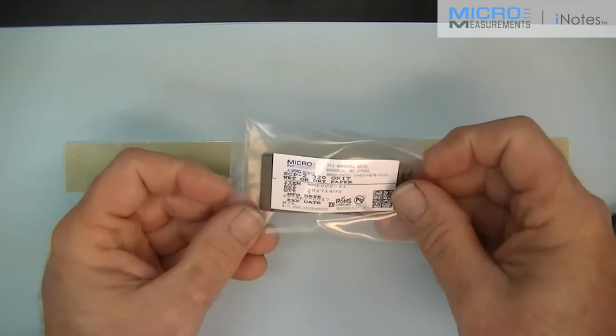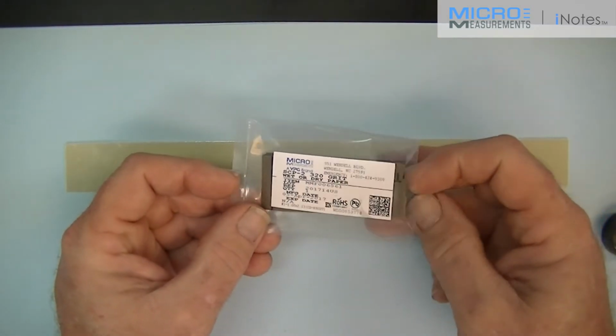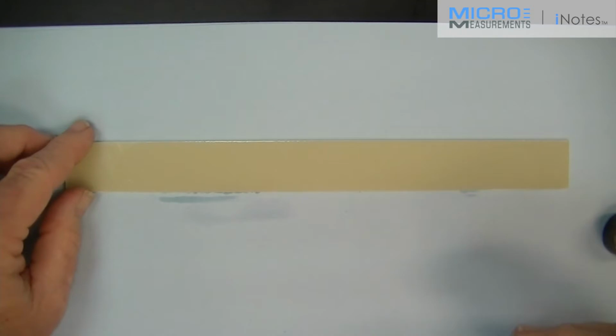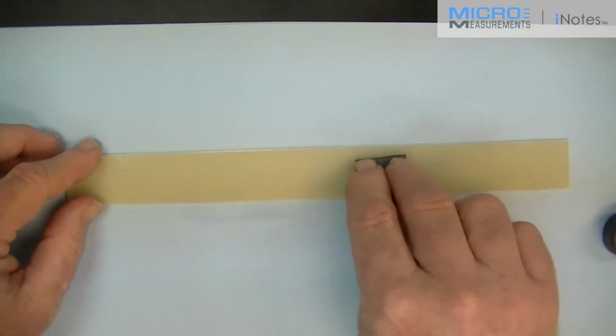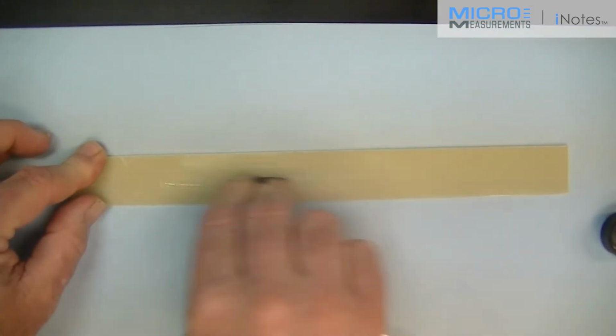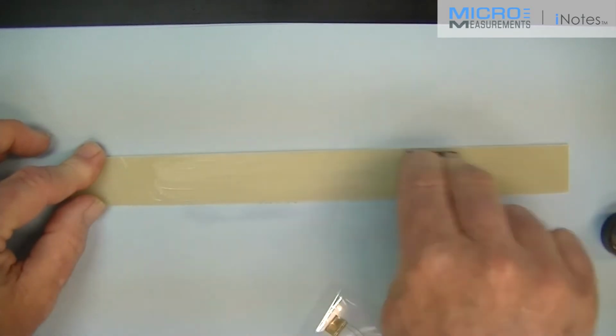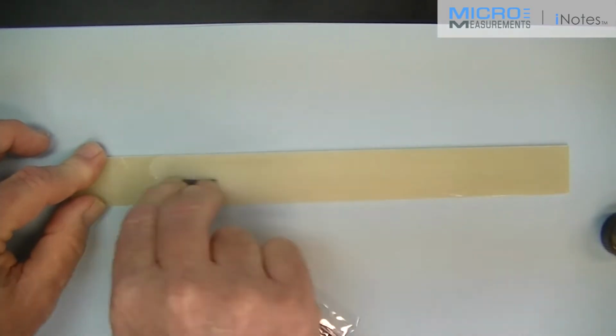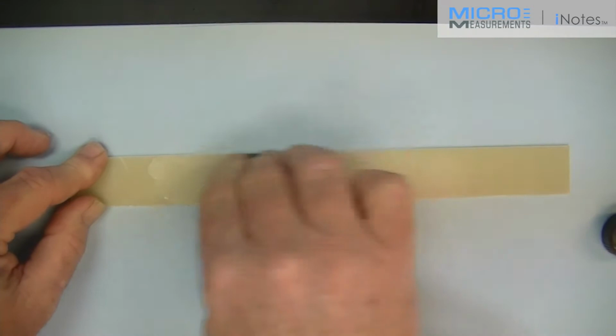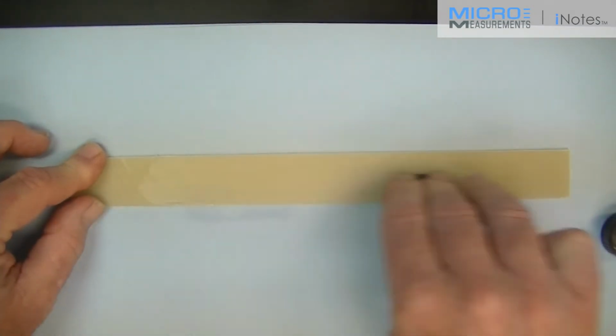The next step is to locate the SCP2, the 320 grit silicon carbide abrasive paper, and I'm going to tear off a single fold about 2 inches long, and I'm going to dry abrade the beam. Ten or 12 strokes is sufficient. We just want to make a little surface roughness.